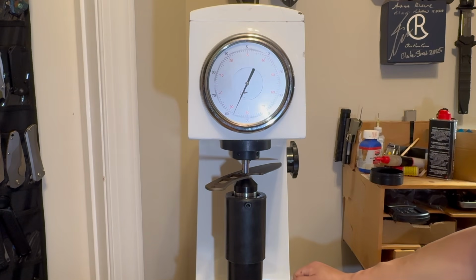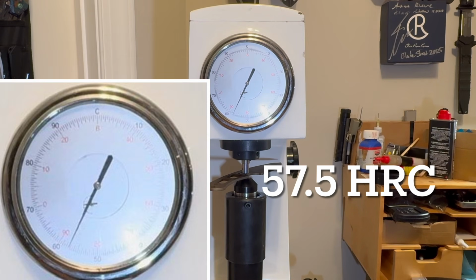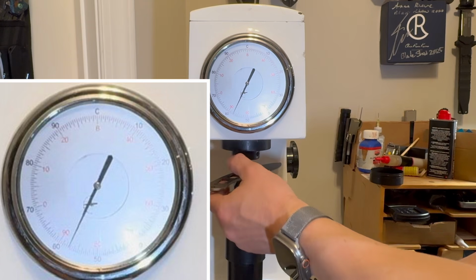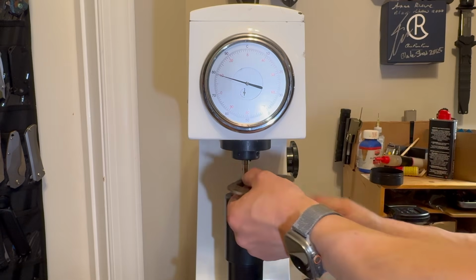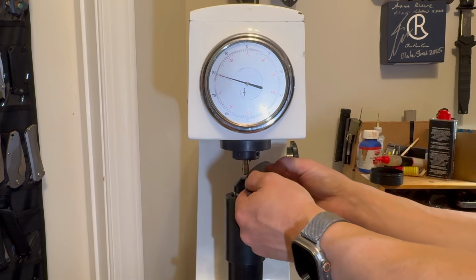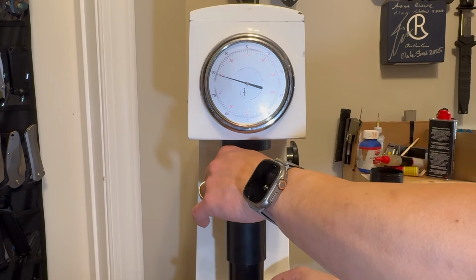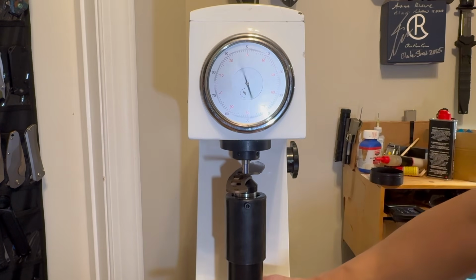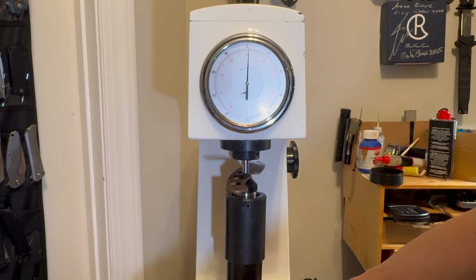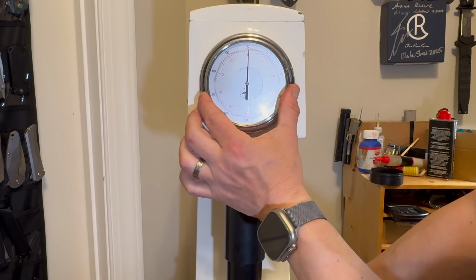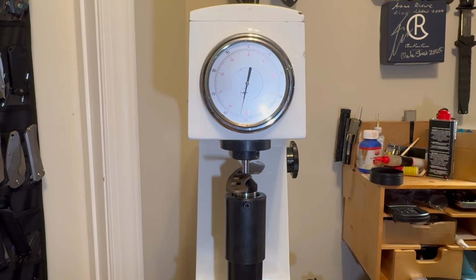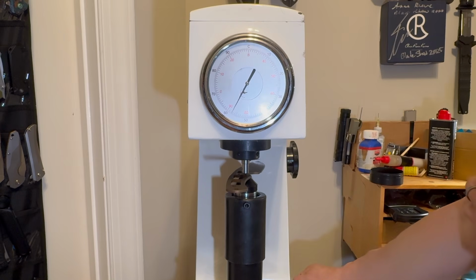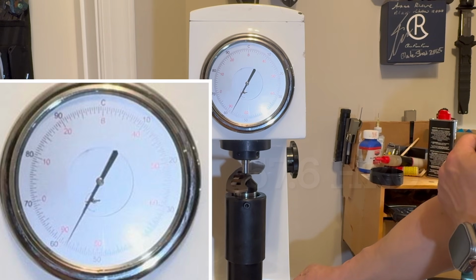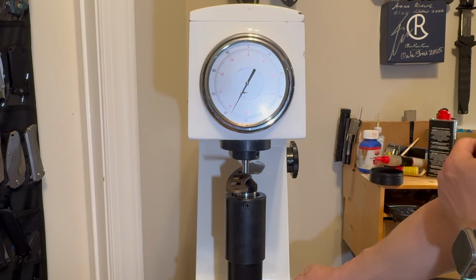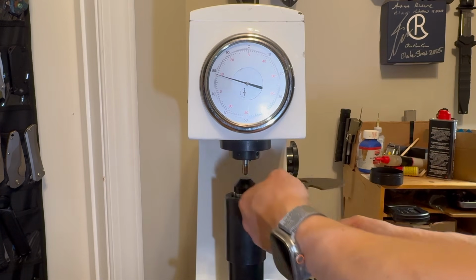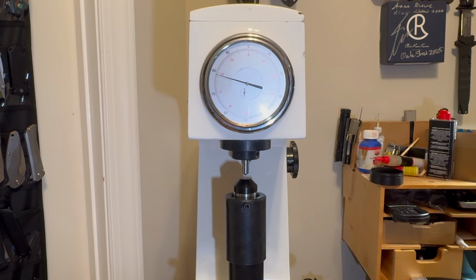Each test takes about 15 seconds, so I'm skipping through that. We got 57.5 HRC this time. And so if the target is 58, it's still a pretty good tight tolerance. But it's lower than I expected, so I'm going to run one more poke, just to be conservative. Oh, and by conservative, I don't mean while wearing khaki pants, tweed jacket, and elbow protectors. I mean being professional, thorough, and diligent. Let's see what we got here. 57.6. So this is consistent with other fixed blades from Buck that I tested.